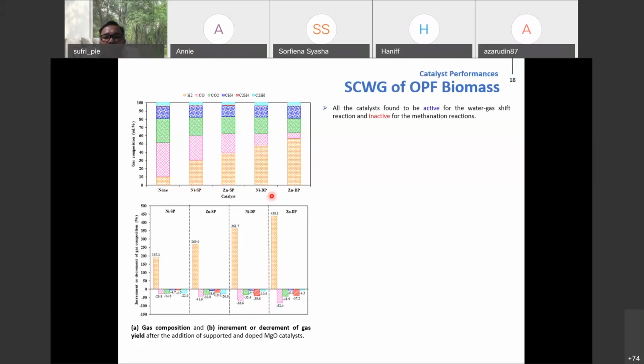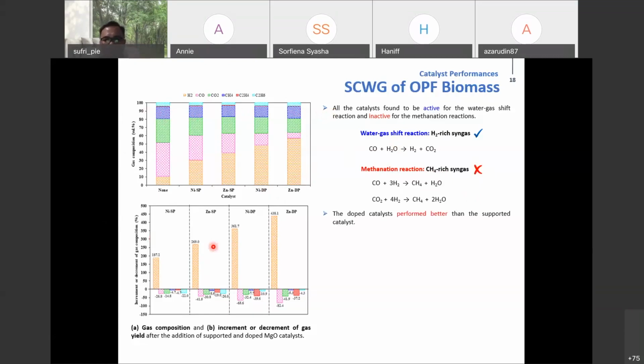All the catalysts that we studied are active for the water-gas shift reaction. If you still remember, the water-gas shift reaction is important and is inactive for the methanation reaction. Why do we say so? If you observe closely, the yield of hydrogen keeps increasing and the yield of carbon monoxide, the pink color, keeps reducing. This agrees with the water-gas shift reaction. However, the methanation reaction is not activated. This is why you observe the blue color, the methane yield, remains unchanged throughout the different types of catalyst. So the catalysts that we reported are active for the water-gas shift reaction, but not active for the methanation reaction.